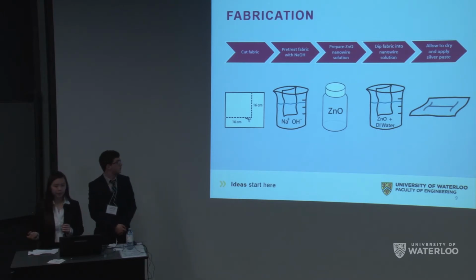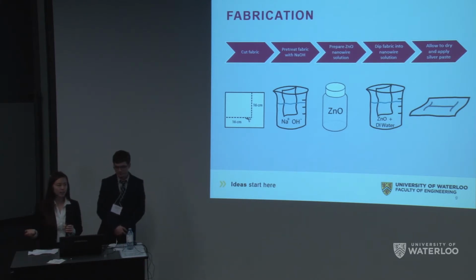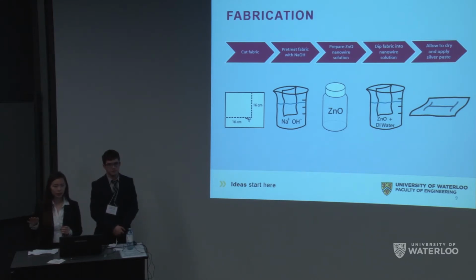1, you have to prepare the ZnO nanowire solution. 2, you submerge the fabric in the nanowire solution to coat it. 3, you allow it to dry and apply colloidal silver paste as contacts. And we realized that the success of our fabrication would also be dependent on our ability to achieve even dispersion and suspension. So we worked on refining our suspension technique.